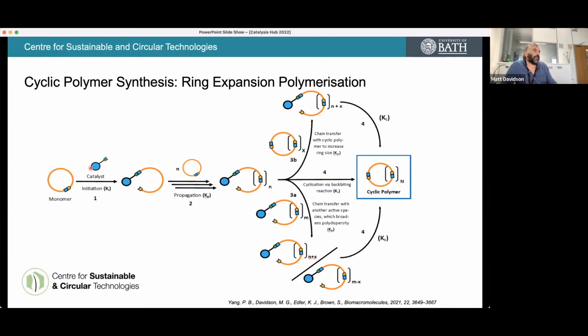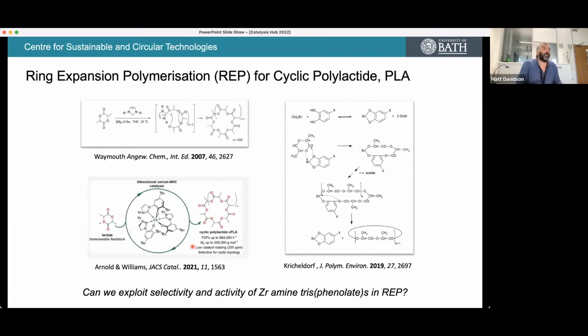And this is typically a catalytic process where you insert the catalyst into a monomer or a particular size ring. And propagation of that to give you whatever catalytic material here takes place, it can be a living type process, until you then get cyclization and get the catalyst back again. So it's not unrelated to living ring opening polymerization, but subtly different. I don't really want to go into the details of the kinetics here. But the point is that ring expansion polymerization is a really interesting technique for making pure cyclic polymers.